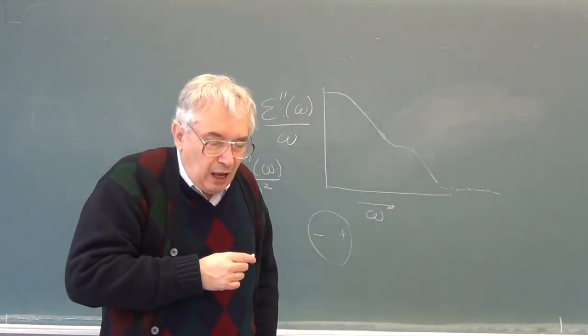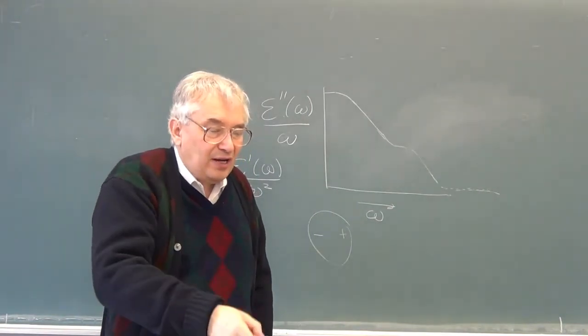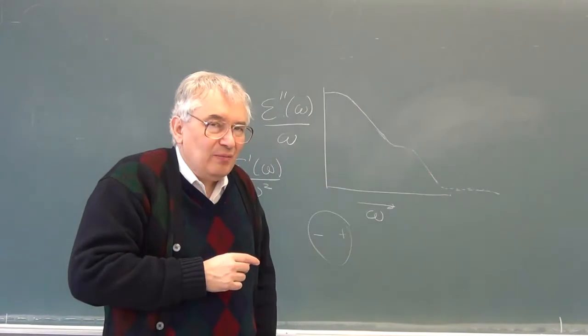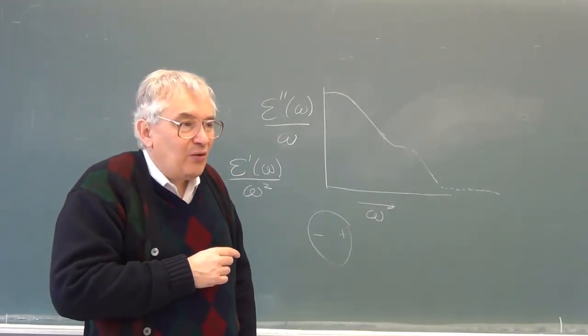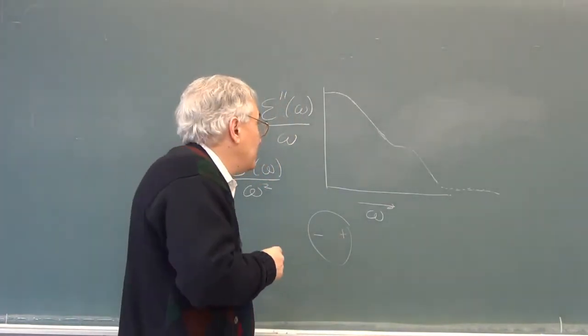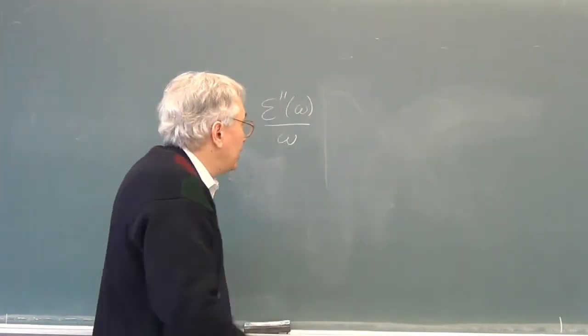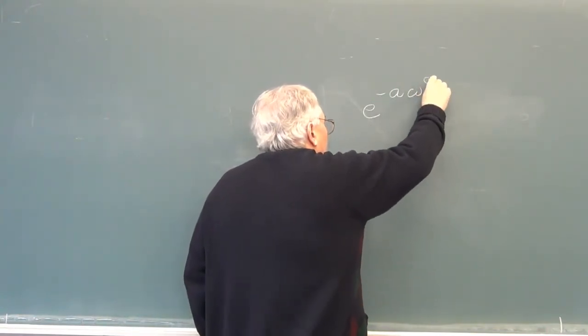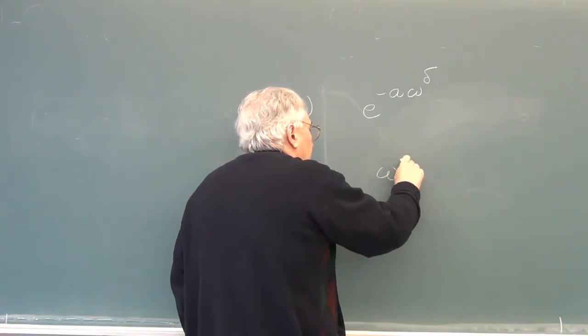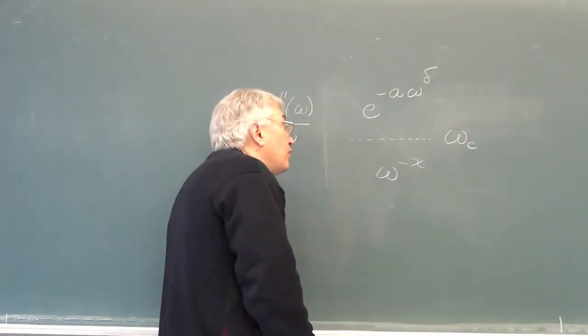What I've chosen to plot is epsilon double prime of omega divided by omega. If we had information on the dynamic response function, you would be looking at epsilon prime of omega, and the reasonable division is by omega squared. The reason for these choices is that dielectric response — frequency-dependent response — in the phenomenological analysis, is subject to the same issues as mechanical response to shear. By direct analogy, these are the functions we look at. We'll get to dynamic mechanical response and viscoelasticity late in the course.